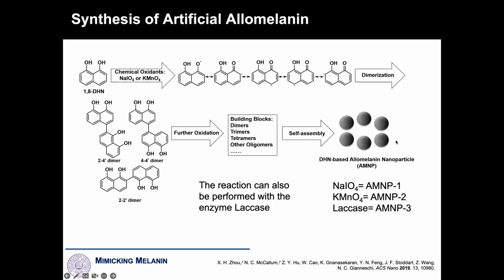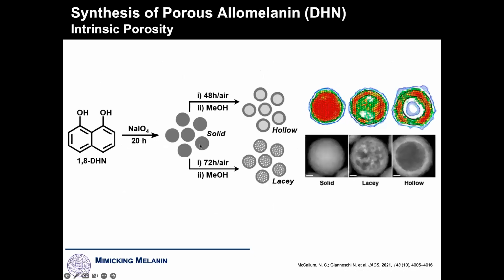These things, over time, can be made to age differently, and they go from gray to black as they cross-link. So it becomes a more and more highly oxidized material, just like when something burns. In this case, we take this species, we oxidize it, and then we allow it to oxidize over time, 2 days in air, 72 hours in air, and then we can etch these particles by a procedure that doesn't really matter. But we can control its porosity.